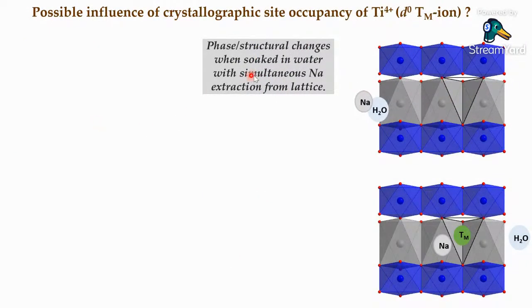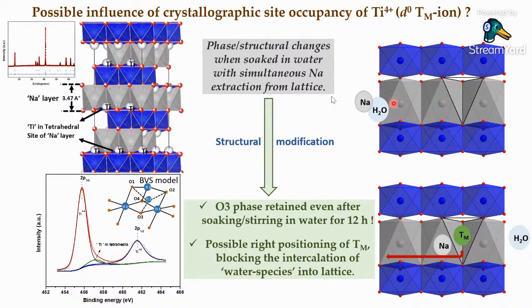Now, again, titanium 4+ is a d0 transition metal ion, so it does not have a site preference for octahedral or tetrahedral site. So some of the titanium ions actually occupied the intermediate tetrahedral site, similar to the way zinc ions had occupied the intermediate tetrahedral site in the case of lithium NMC, the previous example that I had shown.